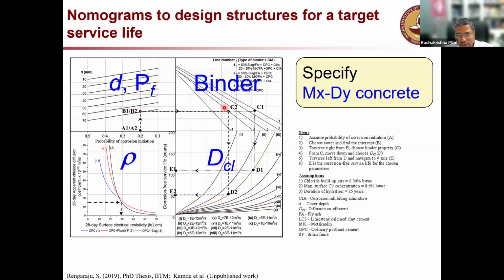And then I draw a horizontal line. And here in this quadrant, I'll pick one of the lines based on the type of cementitious system which I use. This is the binder. Okay. Now, let's say I pick this C1 point, which is 50% slag or fly ash, OPC, corrosion inhibitor, this kind of mix. I can go with this graph here. From there up to here, the structural design office will decide. Then I come down and say, okay, my concrete should have this diffusion coefficient, this curve number 3, I will pick, and then go horizontal, and then this is the 100-year. So if I want a 100-year life, my cover depth is 70 mm. I pick this material 1, or the cement binder choice is 1.